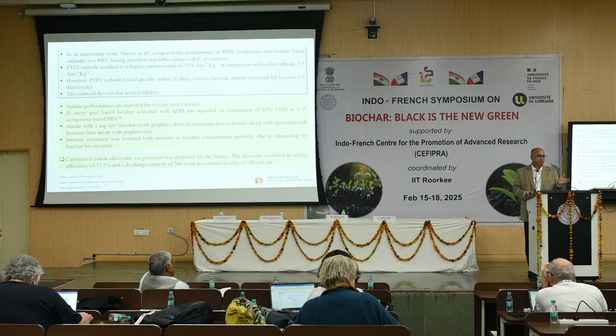Whereas in the case of only PTFE, within 10 days it's gone. It's gone in the sense that it fouled. You have to then remove the fouling using some mechanical method.